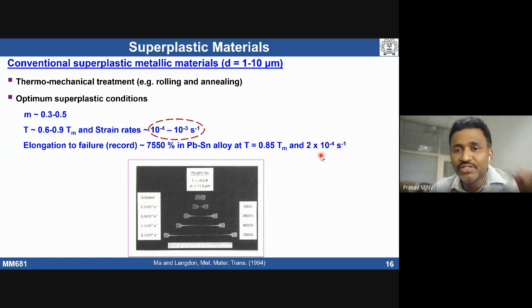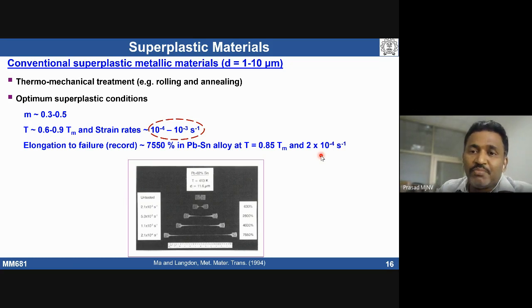So this is one of the major problems. And the other thing: record elongations have been observed in lead-tin alloy, which has no structural application. It's only for soldering. Only a certain class of materials exhibit superplasticity, in a particular temperature window and strain rate range.